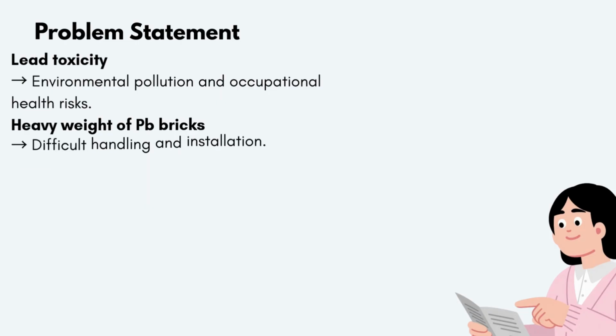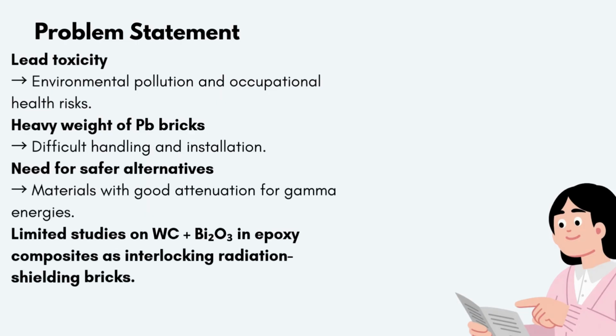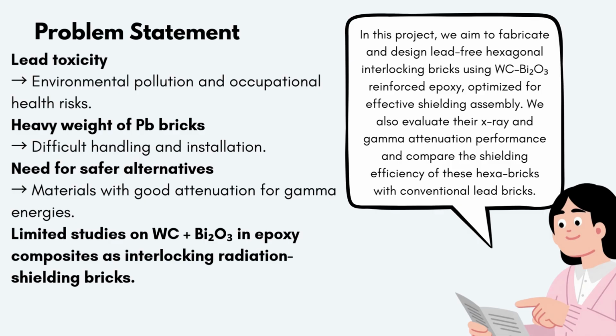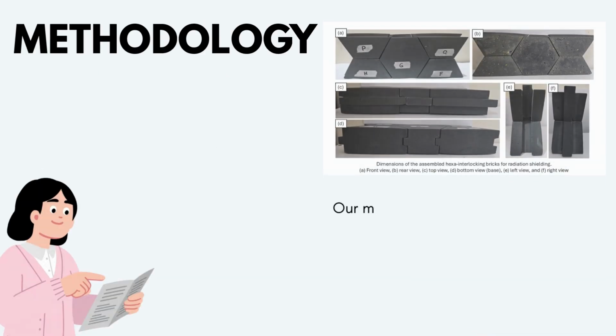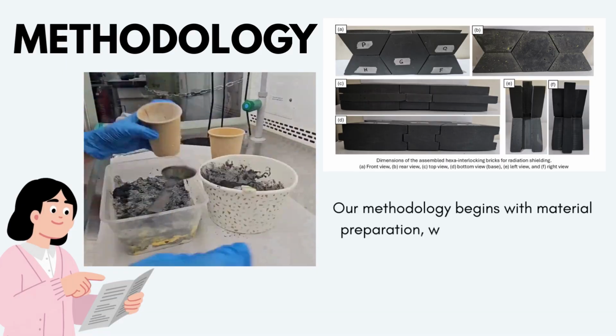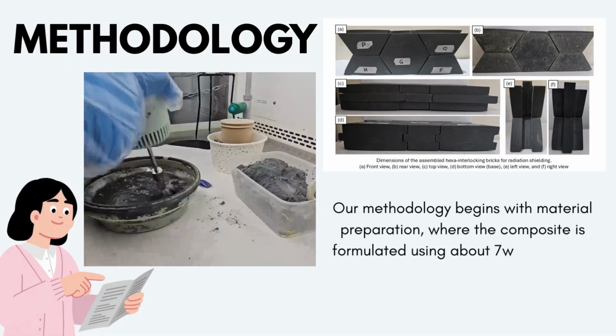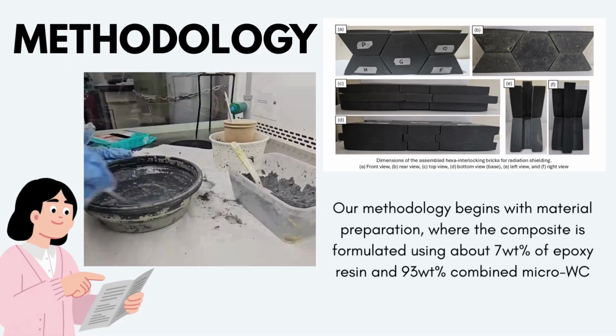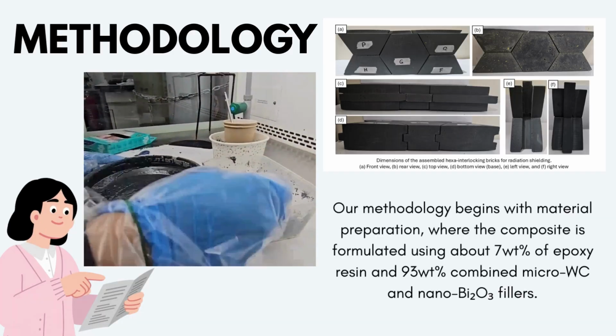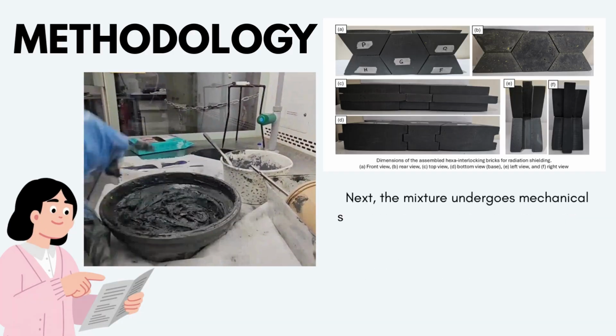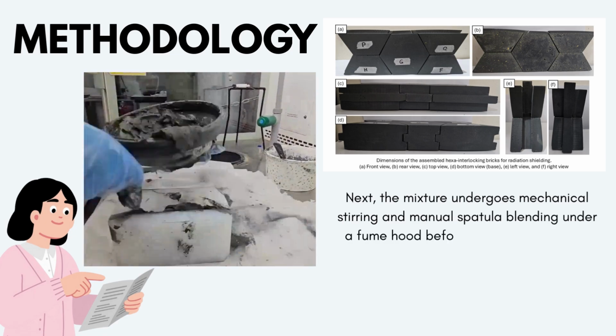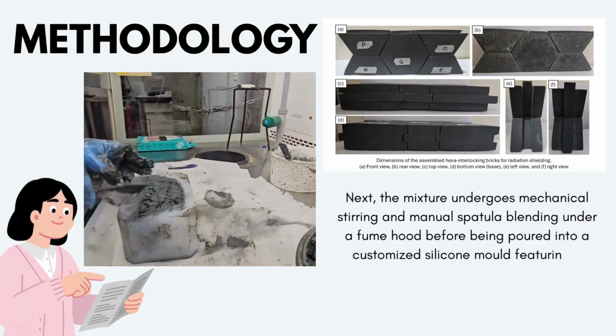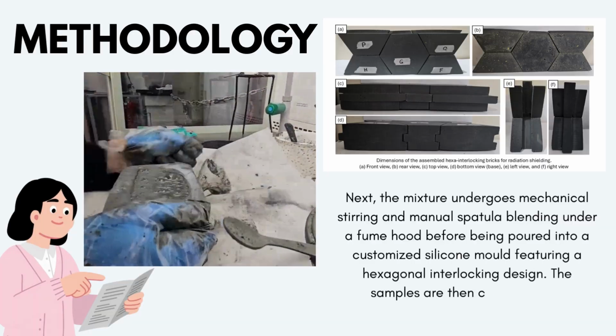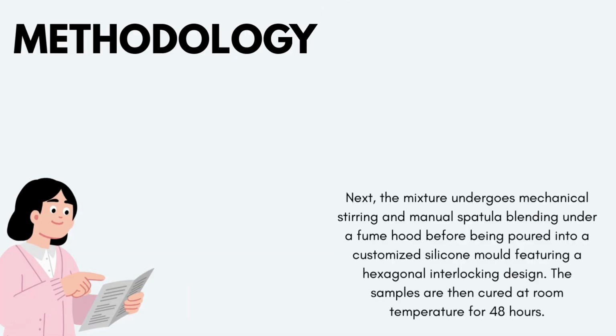Its toxicity and weight cause major environmental and handling issues. We therefore design a safer, lighter, lead-free tungsten carbide bismuth oxide bricks and assess their X-ray and gamma shielding versus lead. Our method starts with preparing the composite using about 7% epoxy resin and 93% combined micro-tungsten carbide and nano-bismuth oxide fillers. The mixture is mechanically stirred, hand-blended under a fume hood, then poured into a custom silicone mold with a hexagonal interlocking design. Finally, the samples are cured at room temperature for 48 hours.